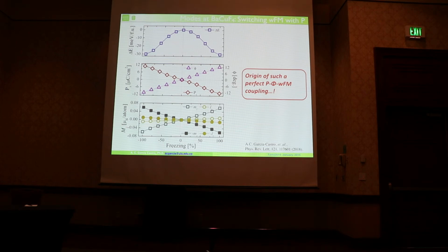But when we switch the domain, and that's something that I will show later, we can see that we can have the opposite behavior. So we go from negative to positive through switching the polarization. So what does that mean? We believe that it's really important: it's a kind of perfect coupling of the polarization with the weak ferromagnetic component, with the weak ferromagnetic moment, through the rotations.